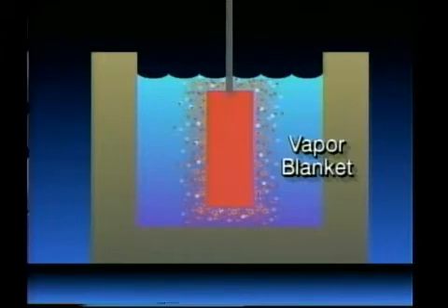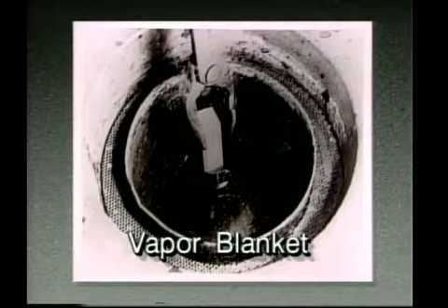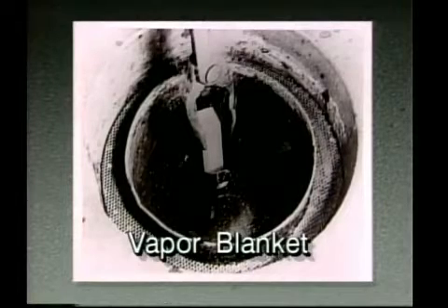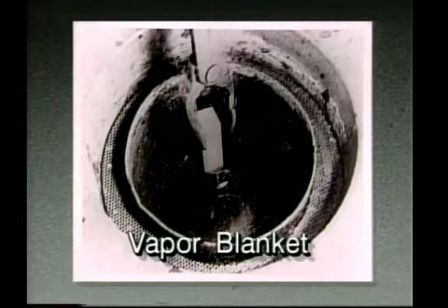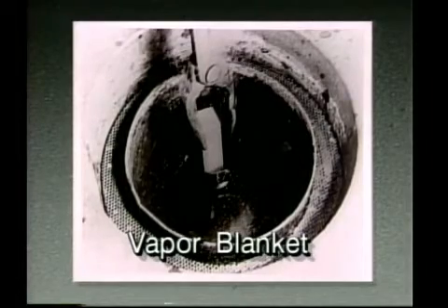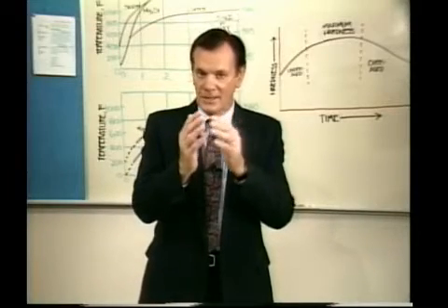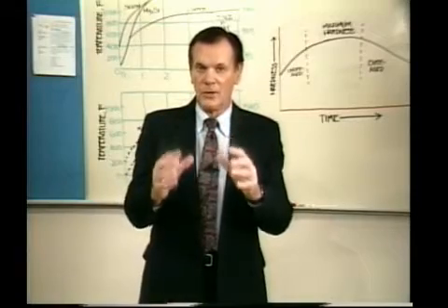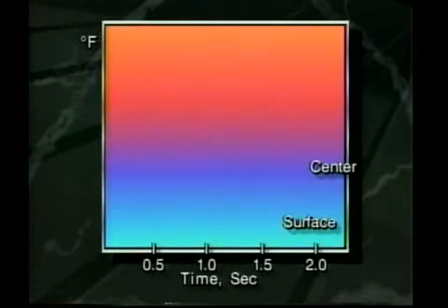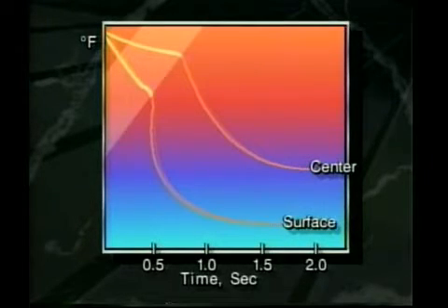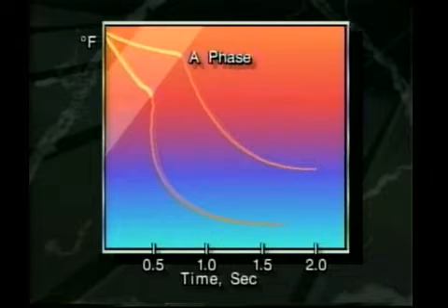A vapor blanket or pocket then forms around the part due to the vaporization of the fluid as it contacts the hot surface. This vapor blanket formation is shown in the photo, which was taken by a high-speed camera during the quenching of a 1-inch by 1-inch aluminum alloy bar. Evidence has shown that there is a continual buildup and collapse of the vapor pocket as the hot liquid first contacts the surface of the heated part, is vaporized, and then backs away due to the formation of the vapor pocket. The entire process is repeated as fresh liquid again contacts the part, is vaporized, and forms a new blanket around the part. The process continues until there is sufficient agitation of the quenching fluid to keep fresh liquid contacting the hot part without forming the vapor pocket. During the A phase of quenching, the cooling rate of the part is extremely slow.